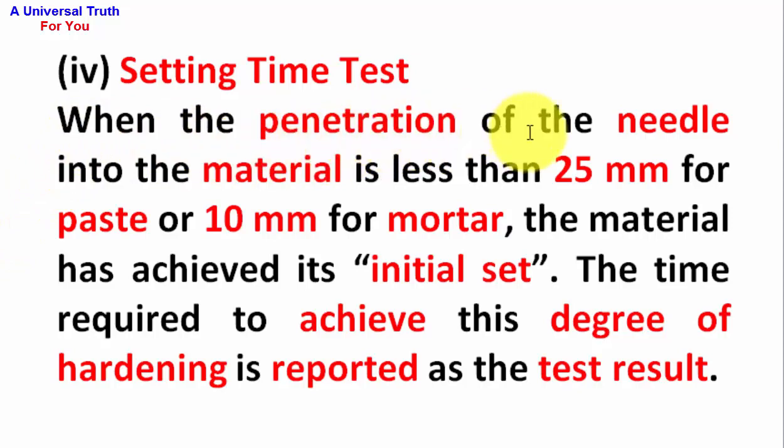When the penetration of the needle into the material is less than 25 mm for paste or 10 mm for mortar, the material has achieved its initial set. The time required to achieve this degree of hardening is reported as the test result.